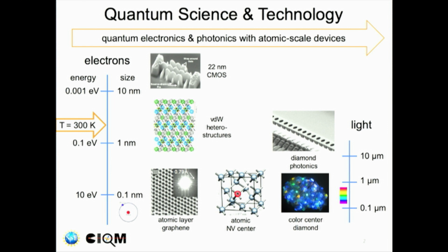All of that sort of got blown up in the year 2004, when Geim and other people were able to make single layers of carbon in a hexagonal lattice just by using Scotch tape, which still works and in fact is still the preferred method for getting the highest quality samples, which is sort of amazing. You just keep pulling it with tape until it's the right shade of gray, and you're right there. And this is a picture of a graphene lattice with a diffraction pattern that shows that it's really an excellent crystal. And in fact, graphene turns out to be amazingly strong, and you can stretch it about 20% before it breaks, which is not true of almost any other thing aside from fresh bread dough or something like that.